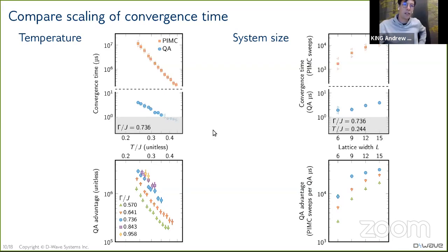And I'll also note that the advantage that we see, this is just this divided by this. So it increases as we get colder, but it also increases as we turn up the transverse field. So the more quantum fluctuations we get, the higher the benefit from the DWave processor. And although we don't have firm evidence, one might easily imagine that this is because of extended tunneling range. So in terms of system size, computer scientists would be more interested in this, and you get more gentle scaling in the DWave processor than you do in path integral Monte Carlo. So you see a scaling advantage in both system size and temperature.